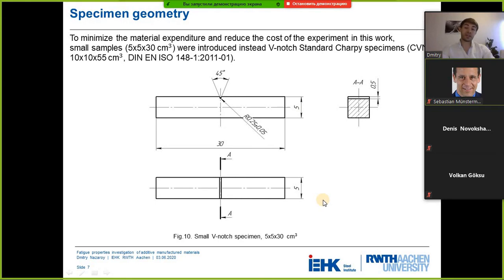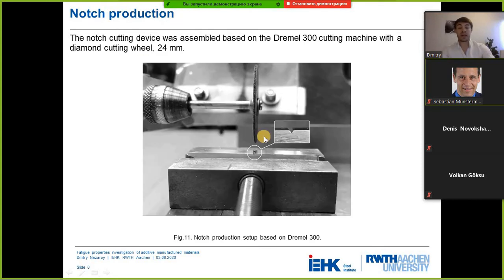So the specimen geometry was chosen like this: 5x5x30 cubic centimeters. In order to produce the notch itself, because the notch was a critical factor, since the notch geometry influenced the incubation period, it was necessary to create equal conditions for all of the specimens. And in order to do that, the notch cutting device was assembled based on a diamond cutting wheel.